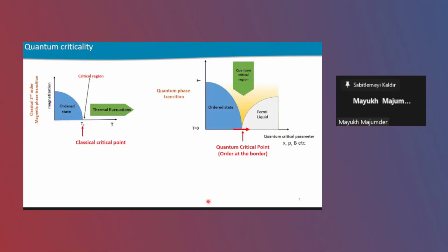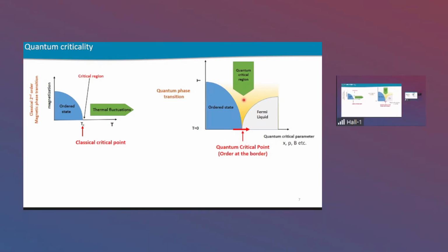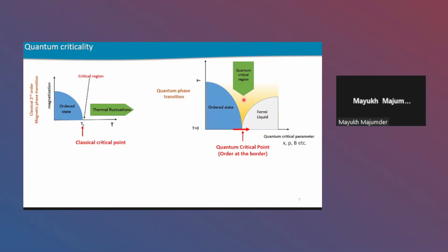Now let us start discussing quantum phase transitions. In analogy to the classical phase transition, in a quantum phase transition you have a non-thermal tuning parameter, for example pressure or magnetic field. If you have a system with long range magnetic ordering at finite temperature, and by applying the tuning parameter you are able to suppress the ordering to T equal to 0, that point is called the quantum critical point. Around it you would expect strong quantum fluctuations. If you increase the parameter further, you would expect some Fermi-liquid behavior and suppression of the quantum fluctuations.